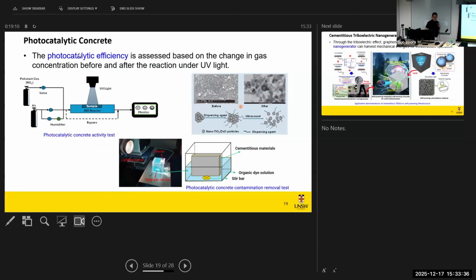So how to evaluate the efficiency of photocatalytic concrete? Basically, during the test, the specimens are treated by UV light. And then the efficiency is assessed based on the changes of the gas concentration before and after the photocatalytic reaction. At the same time, the degradation rate of the dye is calculated based on the solution concentration before and after the test.